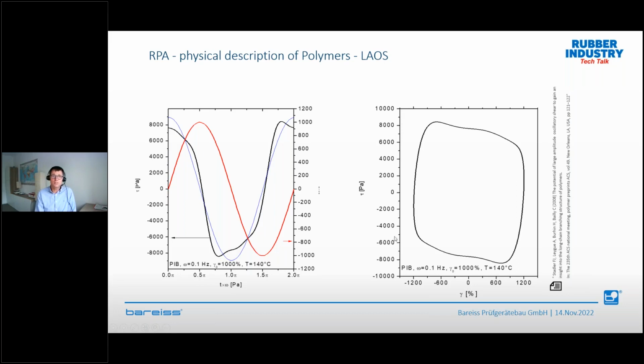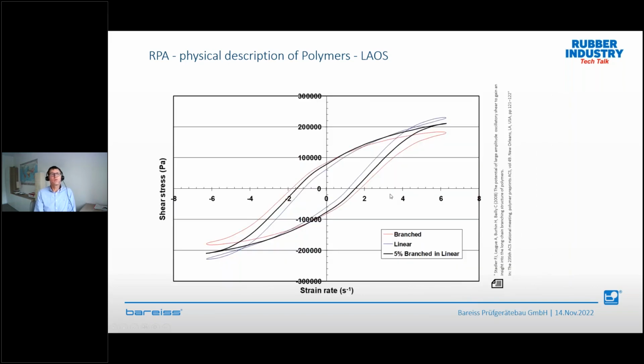If you plot here the shear stress as a function of strain, you get such nice curves, and you see there's some nice information inside. The next plot would be more or less the same. We only change the x-axis from the strain to the strain rate. So time is also very important information here. And then you have such nice graphs. We found that this fits very well for rubber polymers. That means we plot the shear stress again, not as a function of strain, but as a function of strain rate.